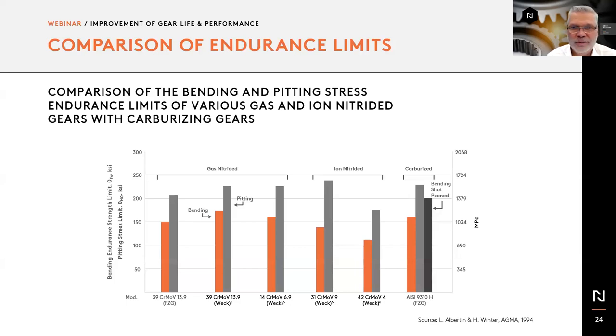Okay, so you have here a general comparison of bending and pitting stress endurance limits for gas nitrided and carburized materials. And what you can see is that typically, pitting resistance may be somewhat similar in carburizing and nitriding, and bending fatigue resistance is much, much better.